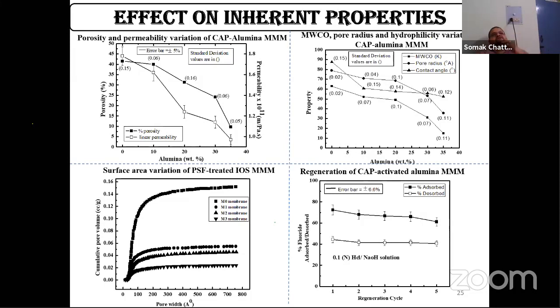Whereas when the phase inversion is taking place, the hydrophilic inorganics which we are impregnating in the membrane usually come up to the top surface, and these are water loving agents. So when they come to the top surface, this attracts more and more water, but the pores are getting reduced. So the pores are getting reduced, but these hydrophilic additives are coming onto the top surface, and therefore it is attracting more and more water. Therefore, the hydrophilicity of the membrane gets increased in this way. There is also a successive reduction in the surface area variation.